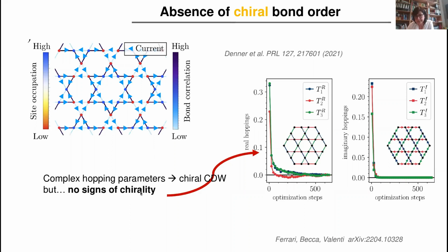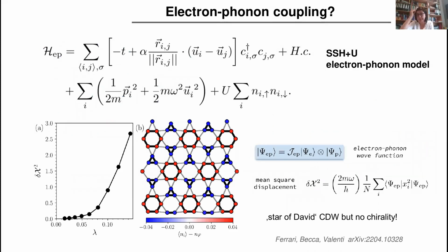In the chirality, the signs of chirality in such phases can be investigated in terms of complex hopping parameters. If we investigate how these hopping parameters evolve, the imaginary part of the hoppings goes to 0. So in principle, it seems if you include this description of correlations into the extended Hubbard model, these chiral phases seem to be washed out.